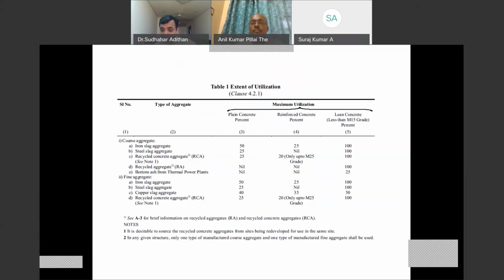important. Table number 1 of IS 383 also restricts you to the extent to which you can replace the natural sand. I find a lot of very high-level researchers, or PG level researchers, attempting something like 100% replacement, wherein you have this stipulation laid by the code book that if you are using iron slag as an aggregate, in plain concrete you can only replace 50%, and in reinforced concrete you can replace only up to 25%.